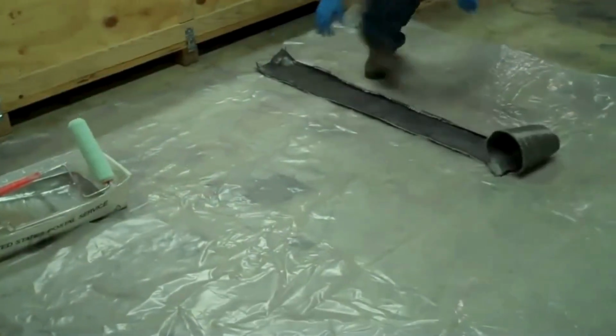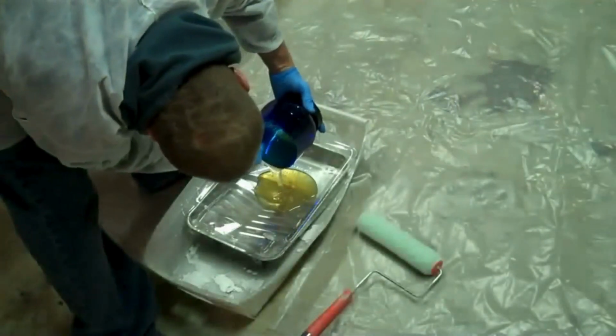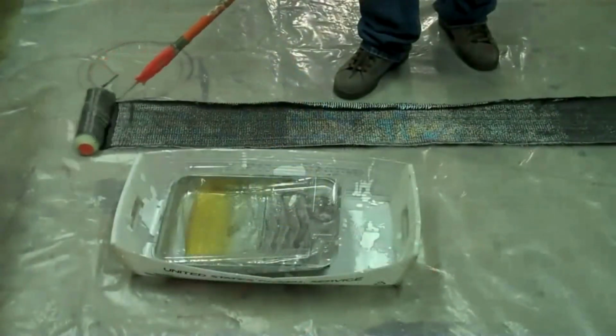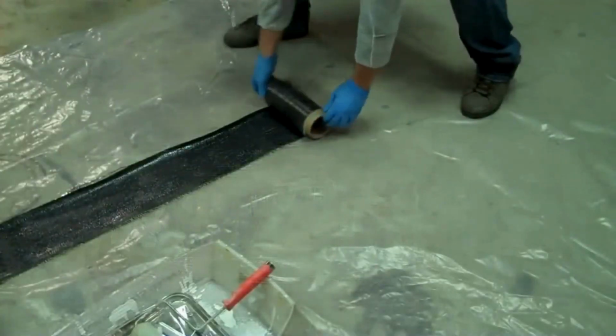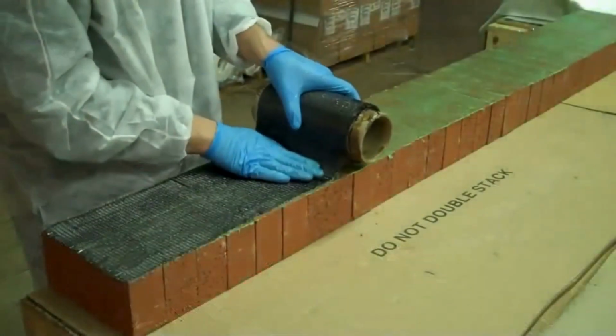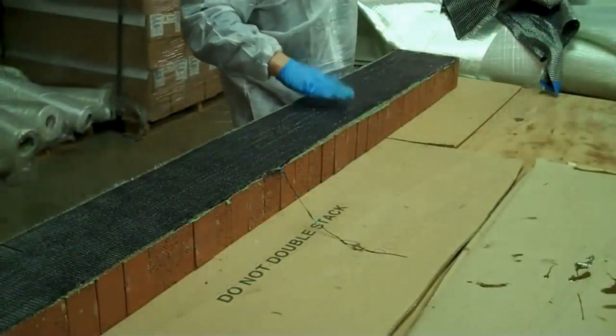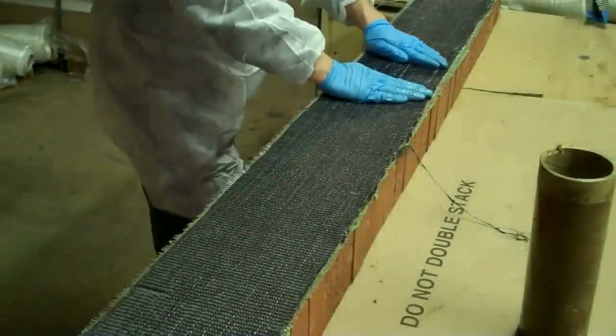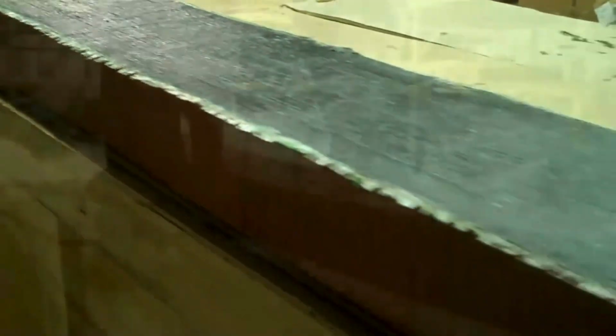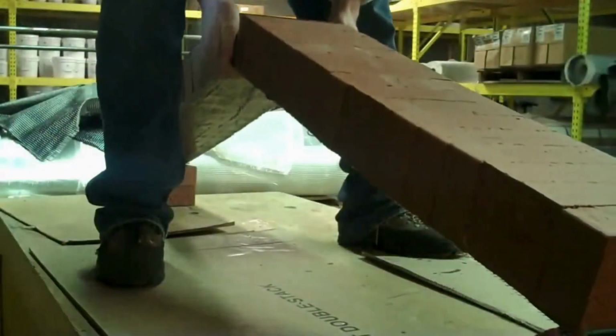Then we take that band of fabric, and with that other resin, which is almost like warm honey, you roll or saturate that with resin and pick it up and put the saturated fabric on the back of the brick. With your gloved hand, you can work out any air bubbles. This takes maybe about half an hour to make this sample. We let it sit in ambient temperature.